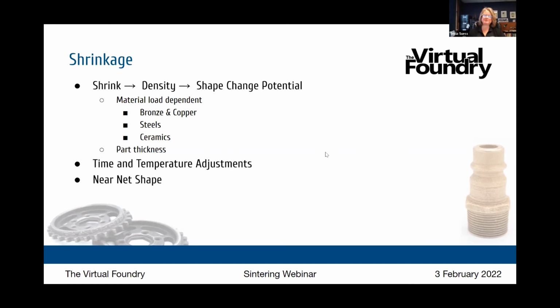So you talked about time and temperature adjustments in order to affect the shrink rate. You can shrink it a smaller amount by holding it for a shorter time. You can shrink it more by holding it for a longer time. So when we talk about the potential for part shape change, metal 3D printing for a part that has tight tolerances should be considered a near net shape activity. So you're getting a part that can go through some final machining, finishing, or whatever else you need to do to get to those tolerances.